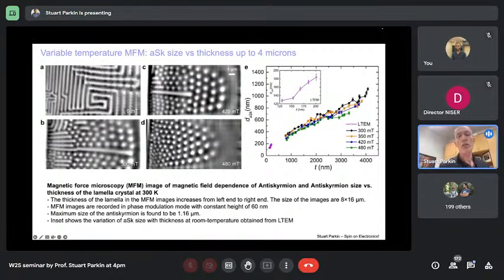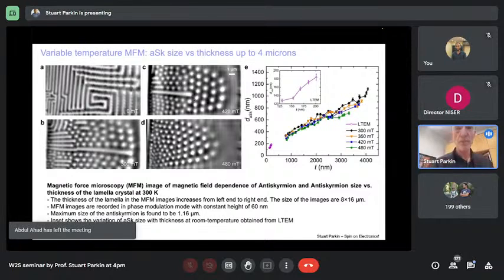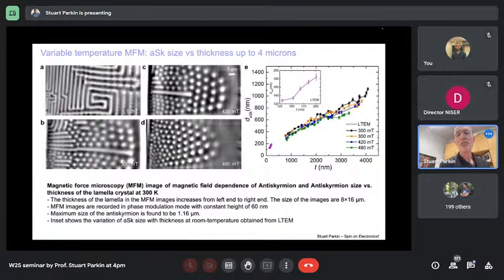And then by increasing the field, we start to see these white blobs. These white blobs are the anti-skyrmions, and we're looking at the magnetization pointing in the opposite direction in the interior of these skyrmionic objects. And you can clearly see that their diameter is increasing from left to right in this image as the thickness of this lamella is increasing from 0.6 to 4 microns. And on the right-hand side, you can see how the diameter changes from 100 nanometers to more than a micron. And then, of course, when they're micron-sized, we can just image these anti-skyrmions using optical techniques.